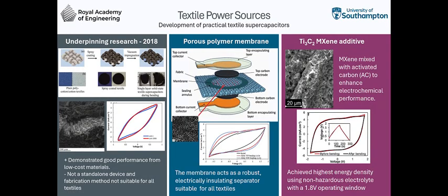This process on the left obviously worked, but you do have to control that coating process. And it's very difficult to do for certain textiles, very thin textiles or textiles that wick and transport that electrolyte very, very rapidly. So we developed a process for adding a porous membrane within the textile. So this SEM just shows the porosity in the membrane, and this just improves the separating performance of the textile. And with this porous membrane, we can turn any textile into a supercapacitor. So you first deposit the porous membrane, you make the membrane, and then you add your electrodes, which sit on top of the textile. And this just shows an exploded view of the current collectors and the encapsulation process, which I'll show in a moment.